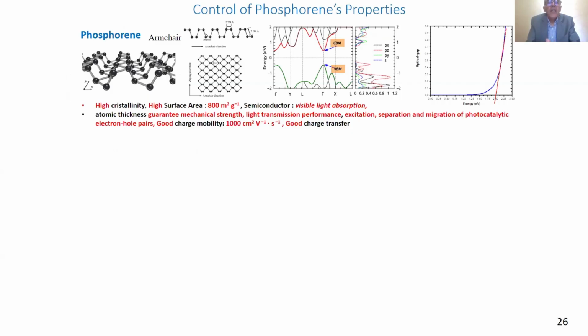This is without the modification, calculated using density functional theory. Very important properties of phosphorene: first, high crystallinity and high surface area, very useful for adsorption and also for photocatalysis, 800 square meters per gram. It absorbs visible light, very important for photocatalysis. Also mechanical strength, light transmission, and good charge mobility, 1000 square centimeters per volt per second.